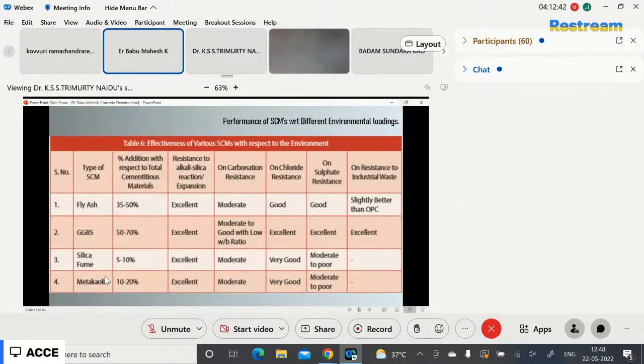In fact, this table is briefing about the effectiveness of the supplementary cementitious materials with respect to the various environmental conditions. Fly ash, slag, silica fume and metakaolin give excellent resistance to alkali silica reaction, chloride and sulfate attack. Except in carbonation resistance, all SCMs give a moderate effect on the concrete, because with a high content of SCMs in the concrete, there is a huge loss of concrete pH solution.